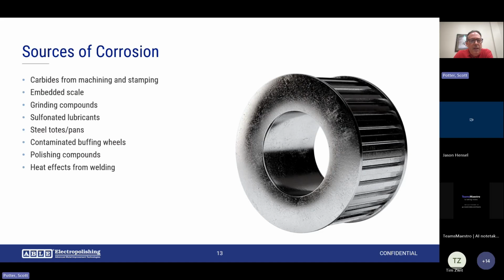One of the things that most people don't realize is when you weld something, you actually change the metallurgical structure of the material. You get what's called carbide precipitation. You're actually drawing the carbon to the surface, and it can compromise its corrosion resistance.